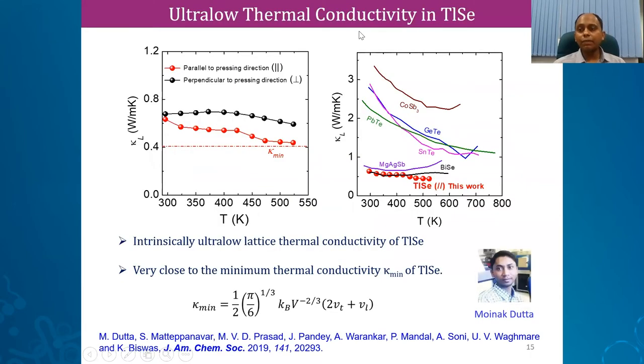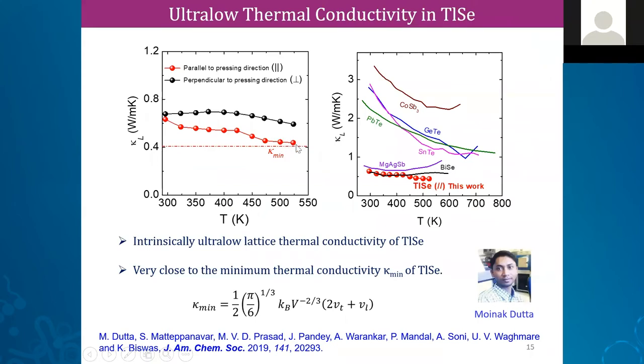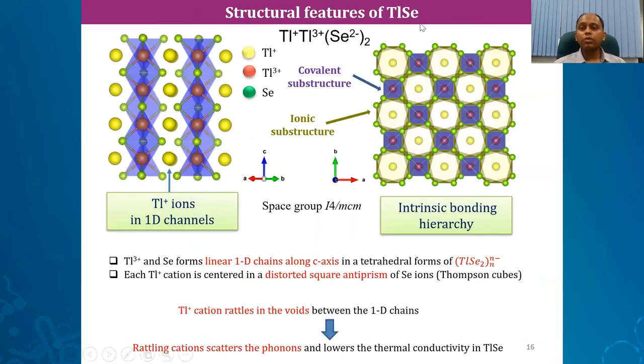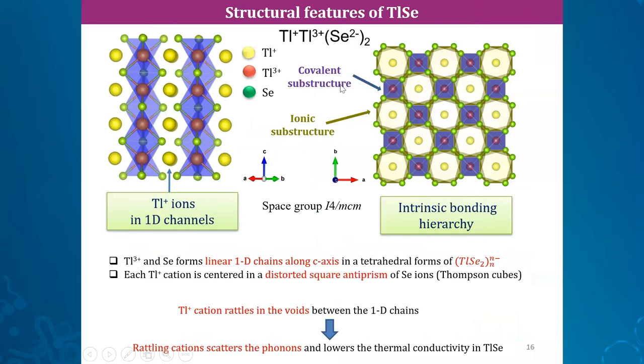The first example is the compound thallium selenide, TlSe. This compound shows ultra-low thermal conductivity starting from 0.6 W/m·K down to nearly the glass limit of 0.4 W/m·K — lower than many state-of-the-art materials — without any nanostructuring, point defects, or doping. To understand why, we need to understand the crystal structure carefully. This work was done by my student Moinak. Importantly, the oxidation state of thallium in this compound is mixed: Tl⁺ and Tl³⁺ with Se²⁻.